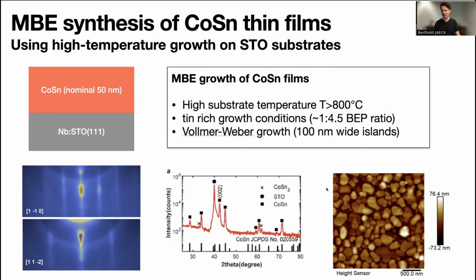because when you, for example, take AFM topographies of such a film, you'll find it's kind of a patchy film with a lot of islands. As a matter of fact, because of the growth kinetics and the relatively weak adhesion of the cobalt atoms and the tin atoms to the substrate, we find that this film now grows in a Volmer-Weber growth mode, where you can still realize 100 nanometer wide islands, but not yet, at least, a continuous film.